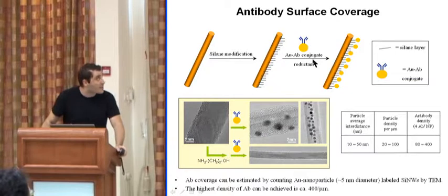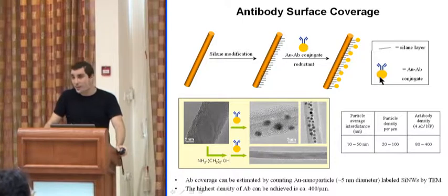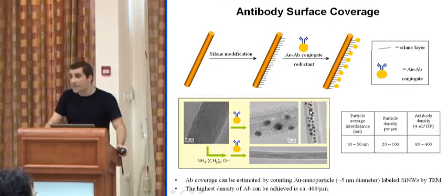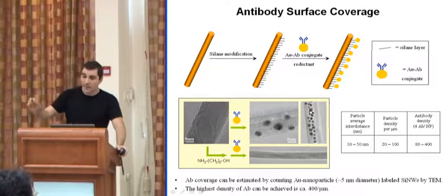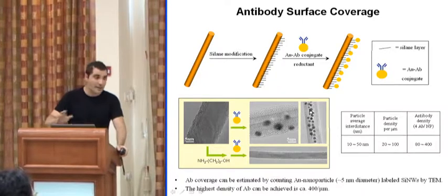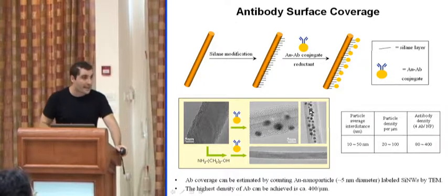The way was that I prepared a conjugate molecule that has approximately a single nanodot per antibody. So after binding the antibodies to the nanowire, we can go to TEM, transmission electron microscopy, and count nanoparticle by nanoparticle, and approximately know the number of antibody molecules on the surface of the sensing device.